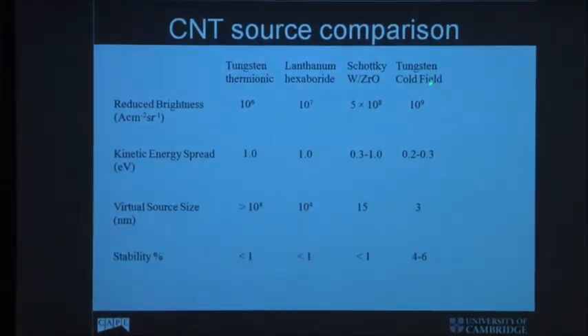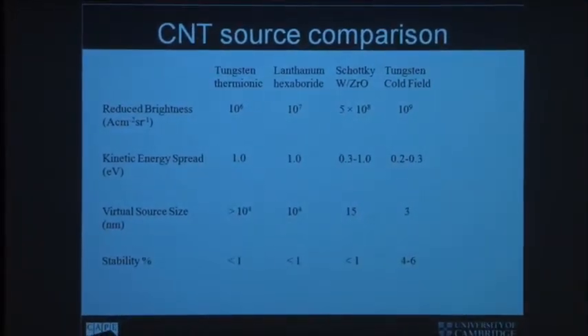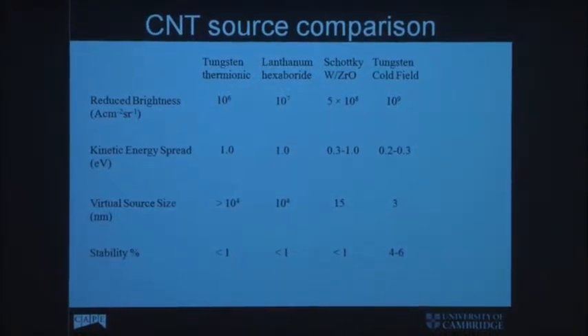So we did this with FEI and with Philips. And what we found was, if you compare it with a typical tungsten thermionic emitter or a lanthanum hexaboride or Schottky or cold field emitter, these are all the ones that are used nowadays for SEMs and TEMs. If you compare the properties, then what you get using CNT is a much higher brightness. This is a funny unit, amps per centimeter square per steradian, but it just means how bright is the signal. Nanotubes are much better than anyone else.